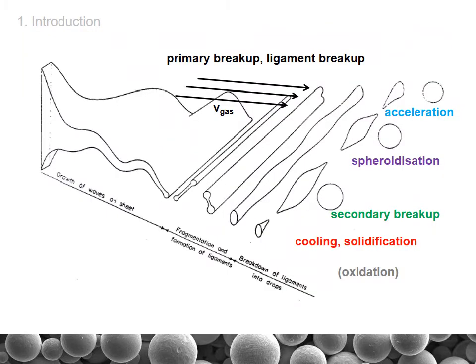If you look into that with more detail, you can see the melt sheet here, which is accelerated by the high velocity gas stream. Due to this high velocity gas stream, some surface waves are built, which a little bit downstream are divided into ligaments, which further break down into these sausage-shaped fragments. These fragments are further accelerated by the gas stream. If the relative velocity between gas and fragments is high enough, those fragments tend to break down into secondary droplets. At low relative velocities, these fragments spheroidize, while at the same time they cool down and solidify. If you have got a little bit of oxygen in your atomization gas, the droplets might also experience some oxidation on their surface.